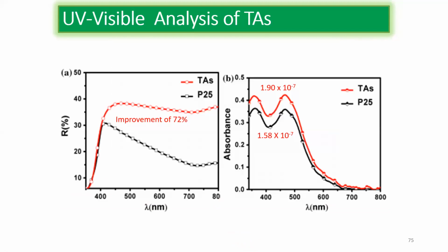And whether light scattering is better or not, we can see by using DRS spectroscopy. Here we see that light is not getting scattered much in the normal particle. P25 is the generally used particle. But when we take our particles, light gets scattered better, almost 72% enhancement in the scattering of the material. So the optical path of the light will be very high in the material that we have synthesized.